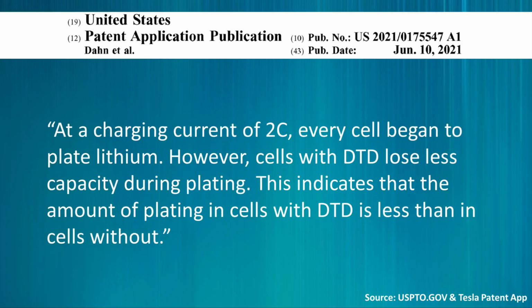When it comes to the reduction of lithium plating during fast charging, they found at a charging current of 2C, every cell began to plate lithium. However, cells with ethylene sulfate lose less capacity during plating. This indicates that the amount of plating in cells with ethylene sulfate is less than in cells without.